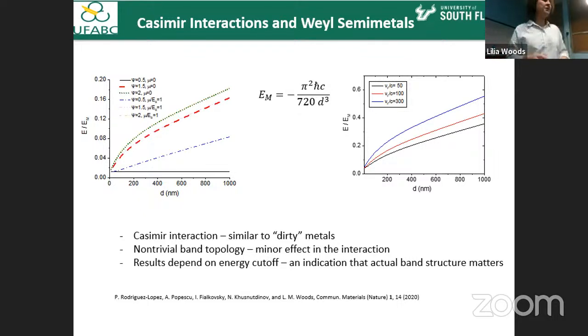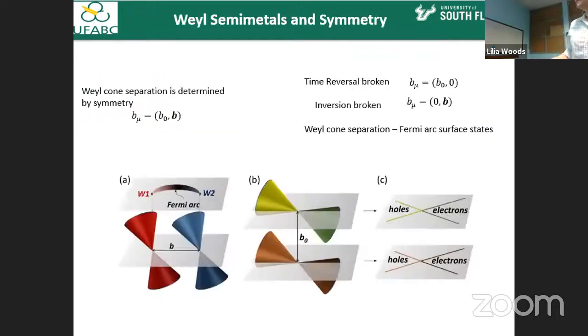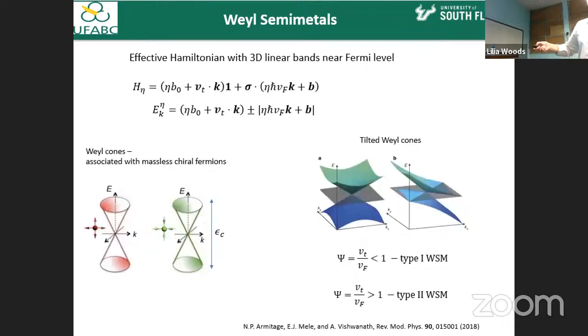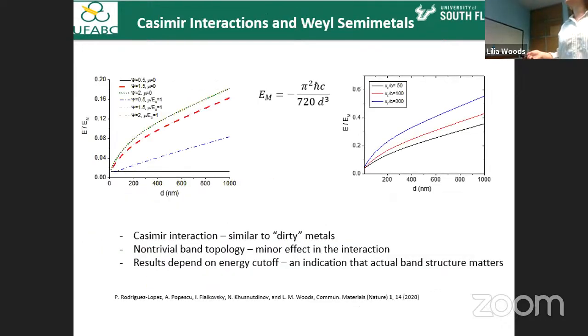One thing, however, that we noticed is that our results depend on a particular parameter, the cutoff energy, that must be present in the model. The cutoff energy is how big the linear dispersion of the Dirac cones is going to be. This is this parameter here, as you can see, so the energy window that I have to assume for the validity of the linear response now enters my model. And there's no way around it.